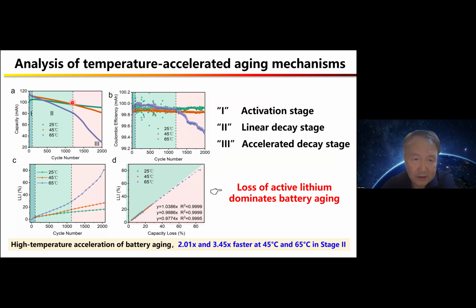We could investigate this degradation stage more clearly. One is the activation stage, the second one is the linear decay stage, and the third one is what we call the accelerated decay stage. But all of these stages are actually correlated to the loss of active lithium inventory, which is linearly correlated with the capacity loss.